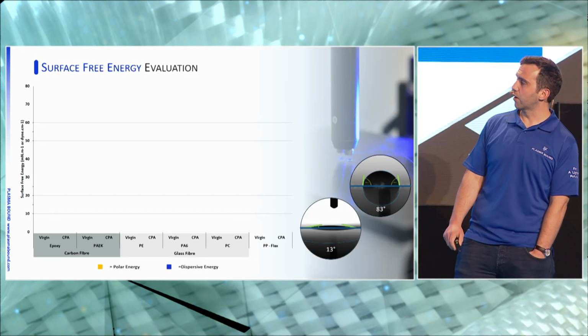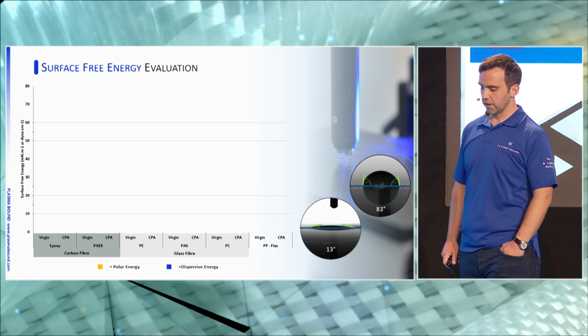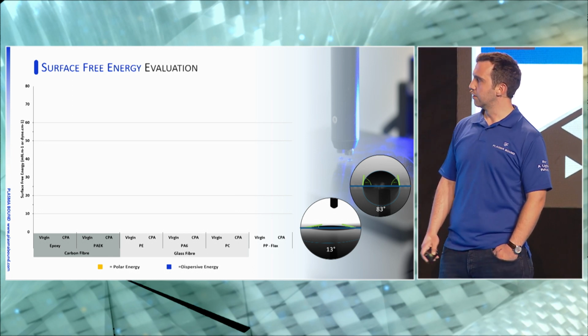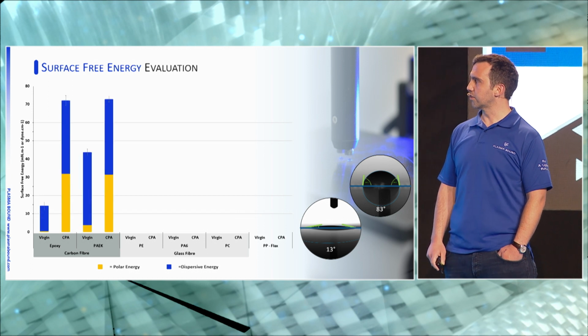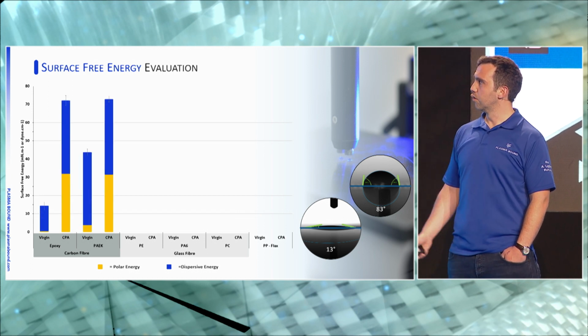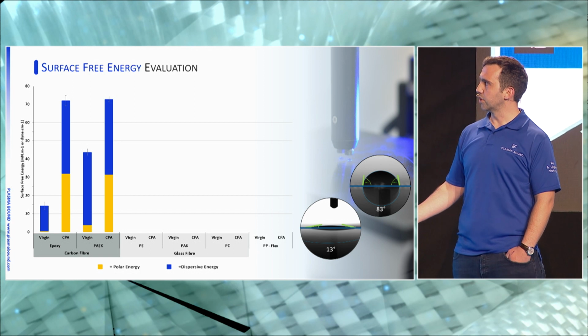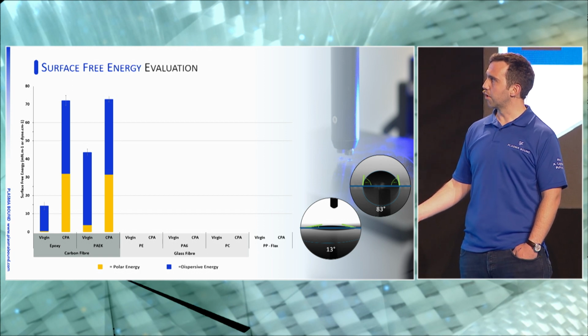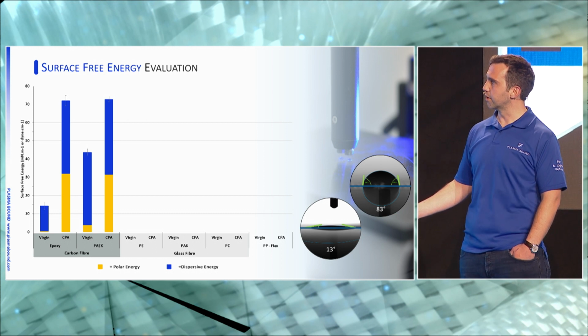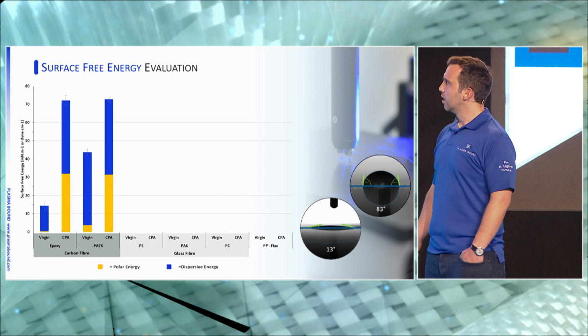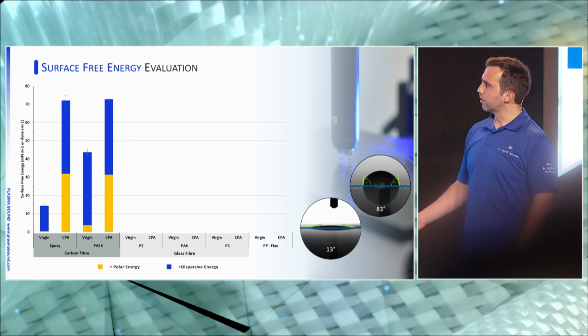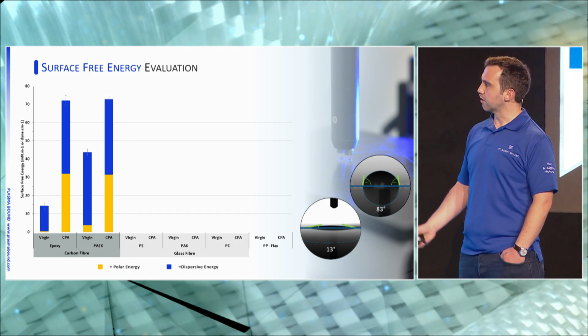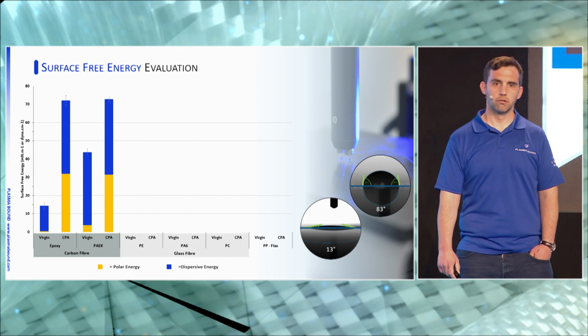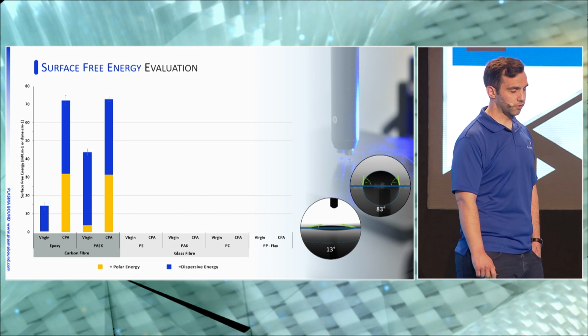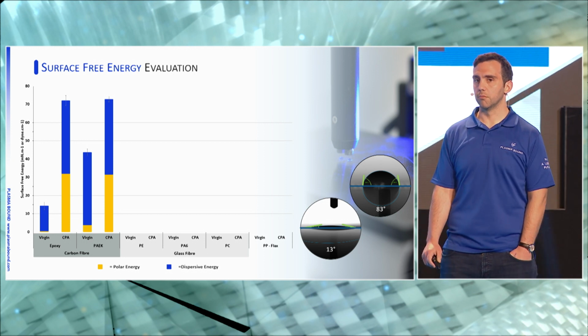And to give you an idea of how the surface energy that we've discussed previously is affected by the CPA process, if you take the virgin of an epoxy system and a PEEK system, we have increased the energies at the interface by a considerable amount, up to 72 dyne, or depending on what your variation is, dyne or millinewtons per meter. And this is in both epoxy and PEEK, PEEK being traditionally an extremely difficult to bond material. So we've prepared it for bonding, and we've actually successfully managed to get it to substrate fail in a bond test.